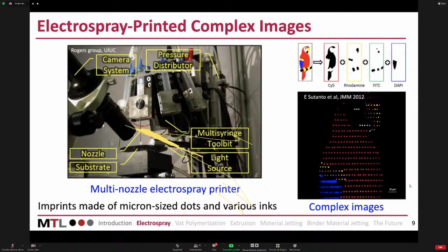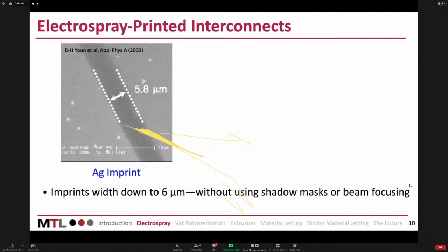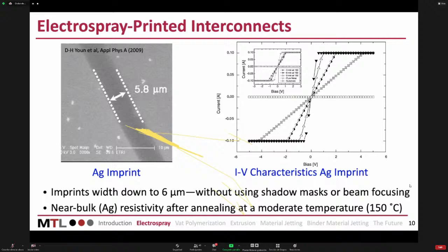So instead of having these 4 colors, perhaps we can think of printing something that has conductive layers and dielectric layers, semiconducting layers, piezoelectric layers. So we're talking right now about making nanostructure electronics or nanosystems. So this is an idea that people have started to explore. And this is an example of work from South Korea, where without any kind of focusing mechanisms, you can make fairly narrow features. So this is just a trace of the order of 6 microns. And then when you measure the electrical conductivity, it works very well. You need to anneal it to of the order of 150 Celsius. But after that, the electrical conductivity is pretty much like bulk conductivity, in this case for silver, which is a very highly conductive material.